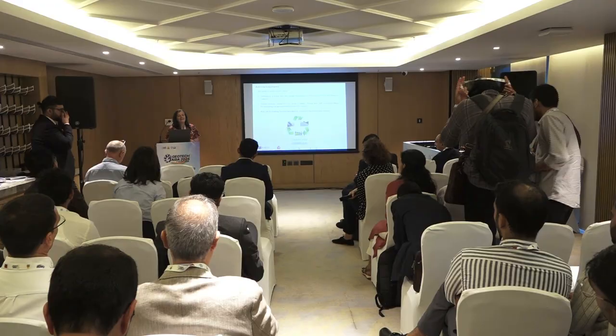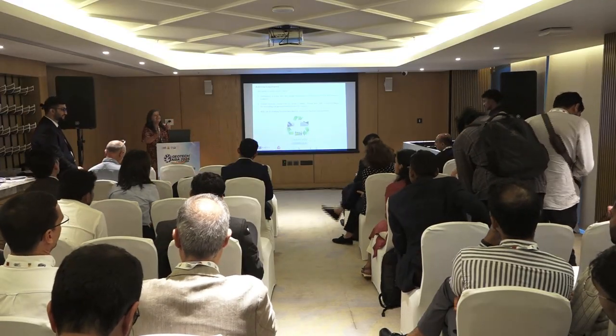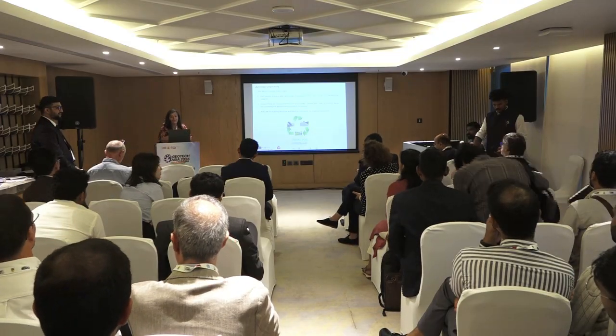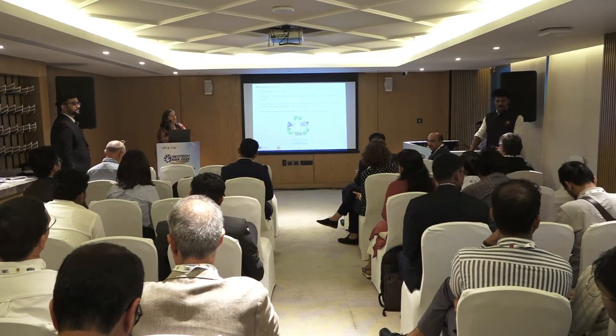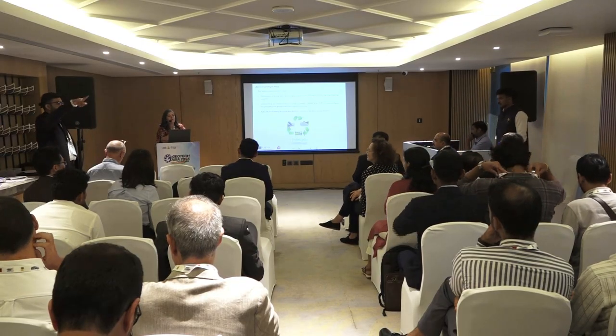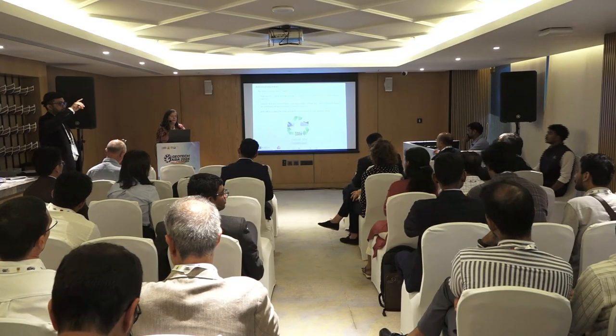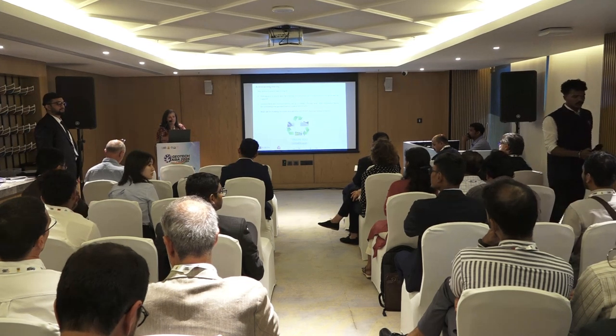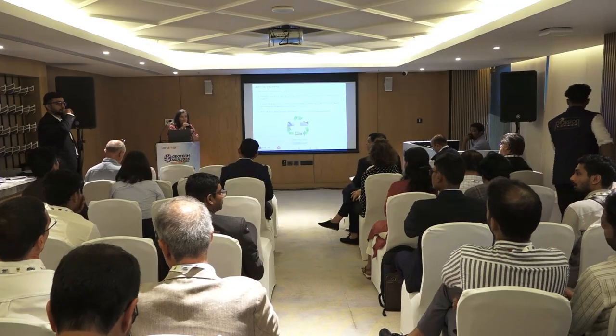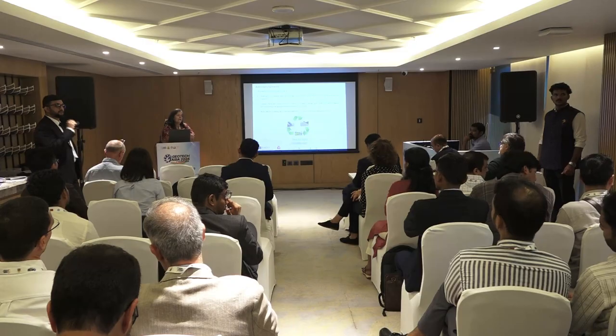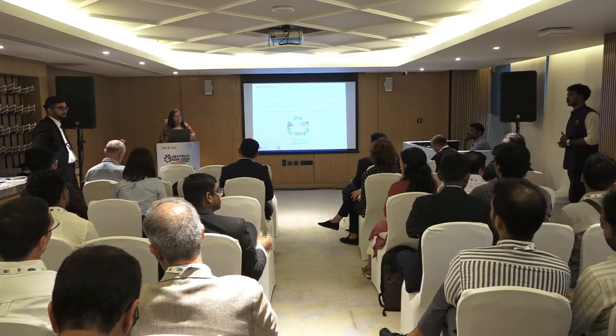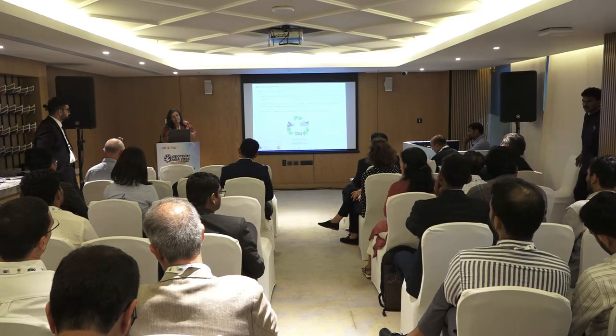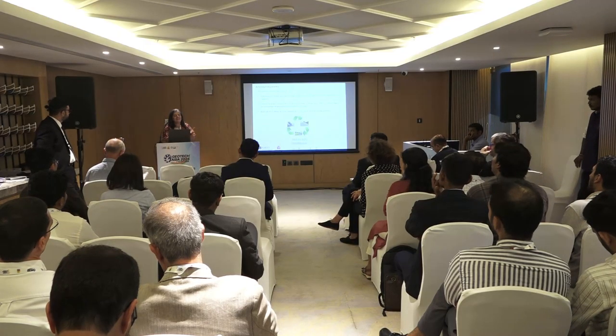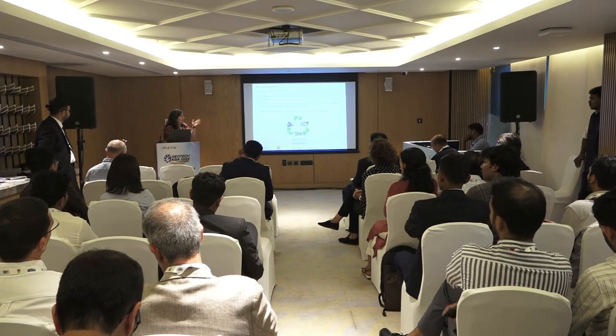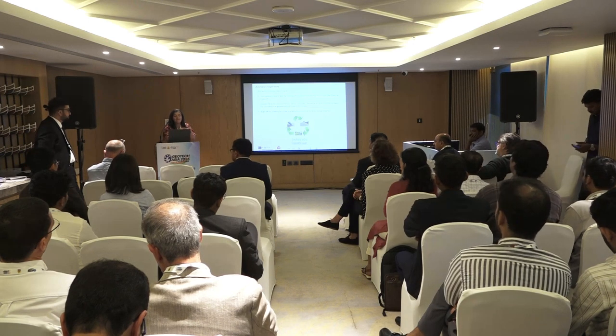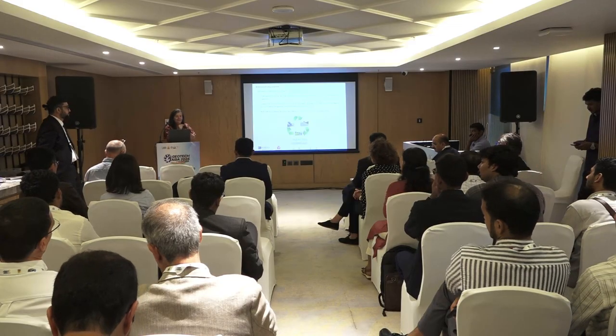I didn't bring these results here, but as you probably know, the results are already published. We also carried out creep failure tests on exhumed specimens and on intact specimens. And what we can see is that, particularly for the geotextile, the exposure to these materials increases their stiffness, because the fine particles of the fill materials remain glued to the geosynthetics, and this means that the stiffness of the material, even for long term, is higher for the exhumed specimens. But we are also studying the long-term effect. I didn't mention that this is only part of a broader research study. I only bring a very small part of the study.